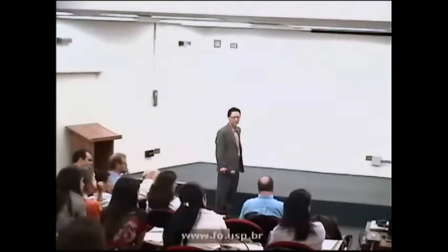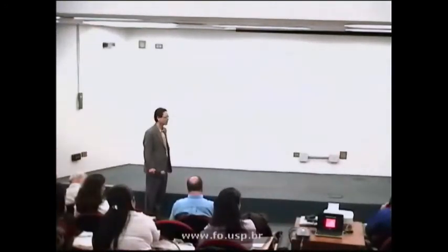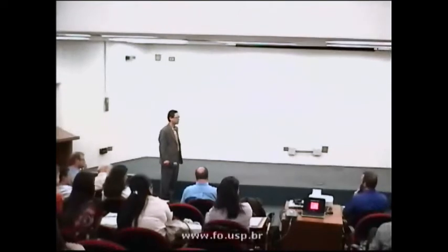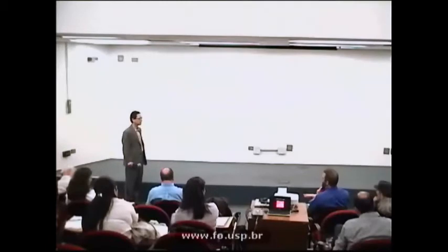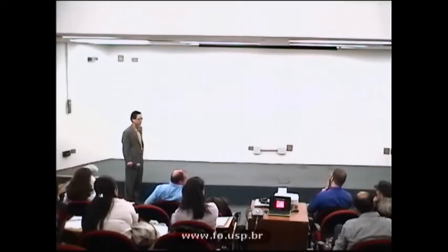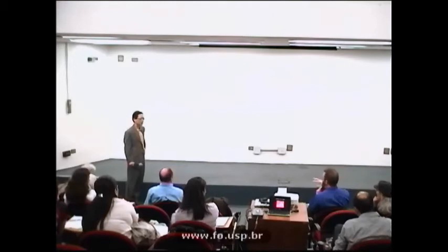Near the beginning of the presentation, you showed, if I understood correctly, on the fatigue loading, the heaviest load on the normal zirconia lasts only 30 cycles or so, as opposed to the clinical case at much lighter load, which lasts a very long time before failure. So I was wondering, do you think there's a possibility that the heavy load changes the ratio of the crack growth mechanisms? For example, changing the contribution of stress corrosion versus water pumping?